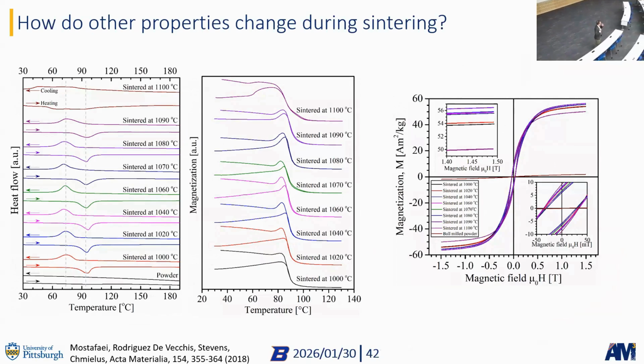Can anybody imagine why that one was different? 1100 C. Anybody want to take a guess? The temperature is too high. We melted our part, okay? So we had a lot of compositional changes there, a lot of evaporation, basically. So we changed our composition. That's why this was not so good. But the cool thing is all the other temperatures and all the other times resulted in the same functional magnetic and phase transformation properties. And that's great because now we can really just focus on our pore microstructure.